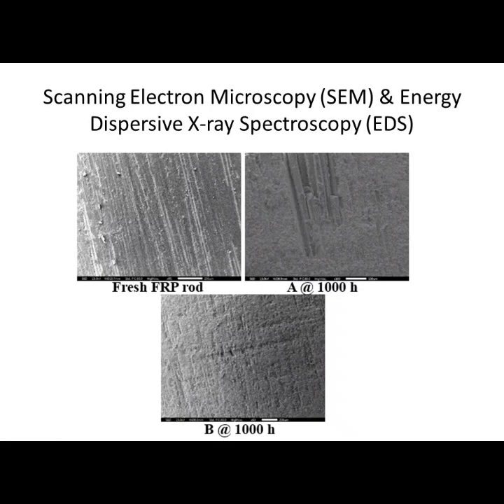For the fresh sample here, we see that the glass fibers are well covered by the epoxy resin matrix, and also the interface between the glass fiber and the epoxy resin is well and intact. However, after the experiment, the normal FRP rod, sample A, shows a severe degradation where many glass fibers are found to be broken and separated from the epoxy resin matrix, and also the remaining epoxy resin matrix was found to be uneven and inelastic with many holes, which could be due to the gas generated during the degradation of the epoxy resin under the impact of the electrical discharges, arcs, leakage current, etc.